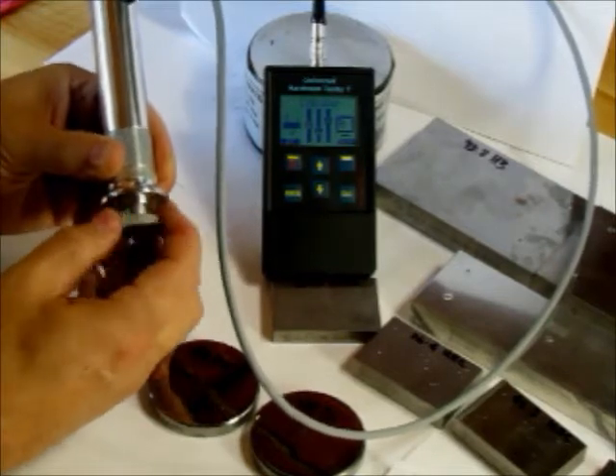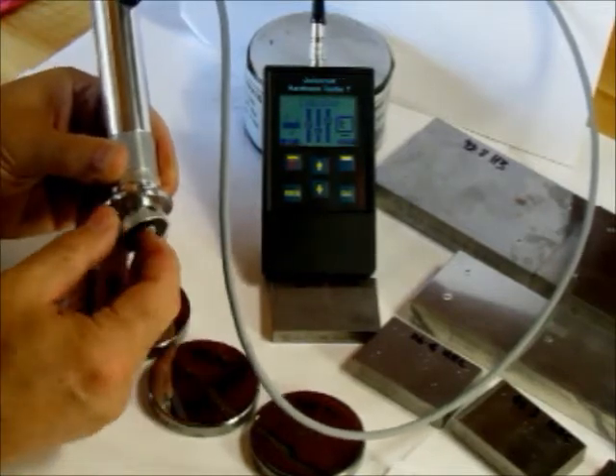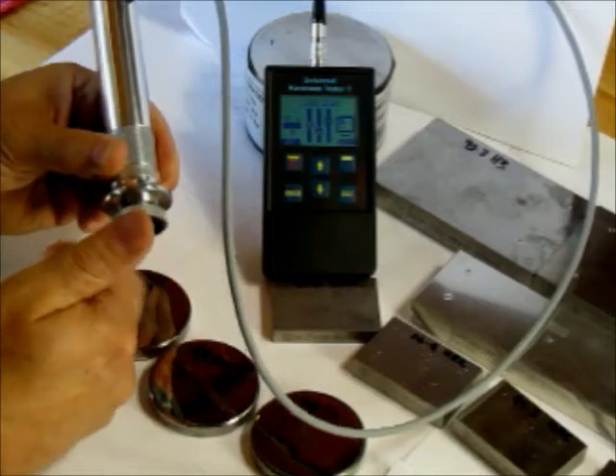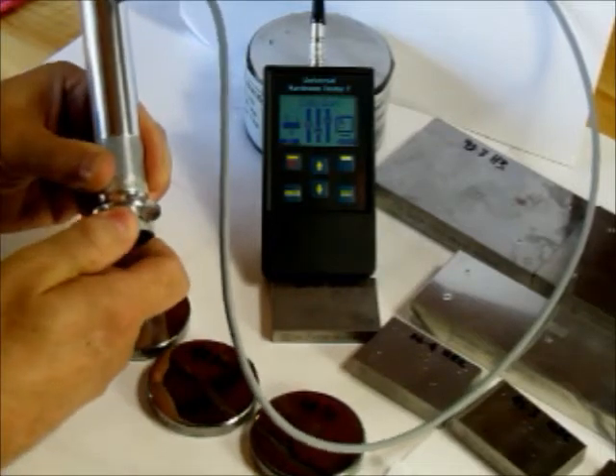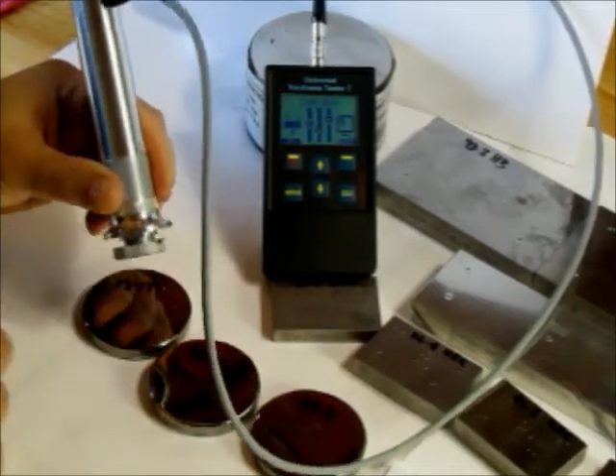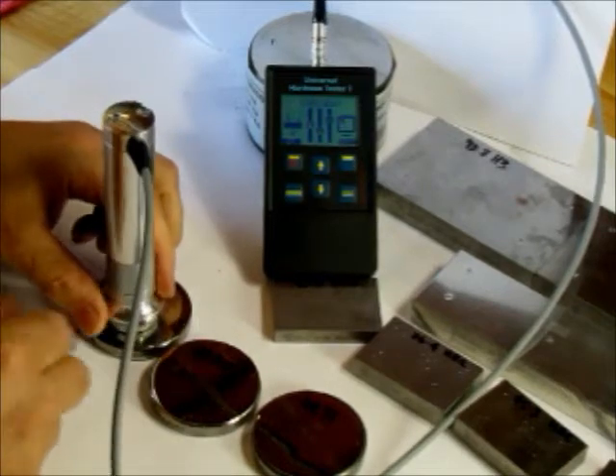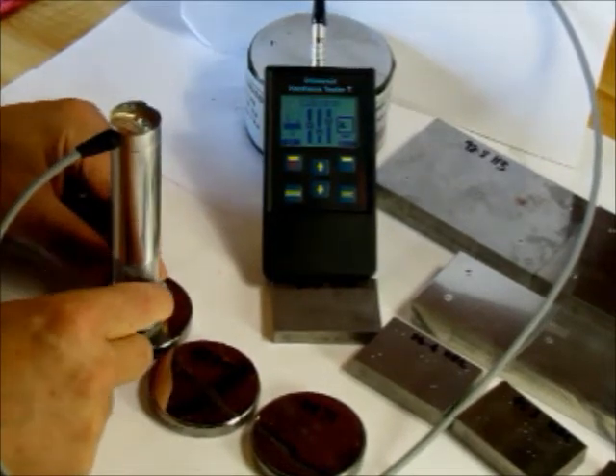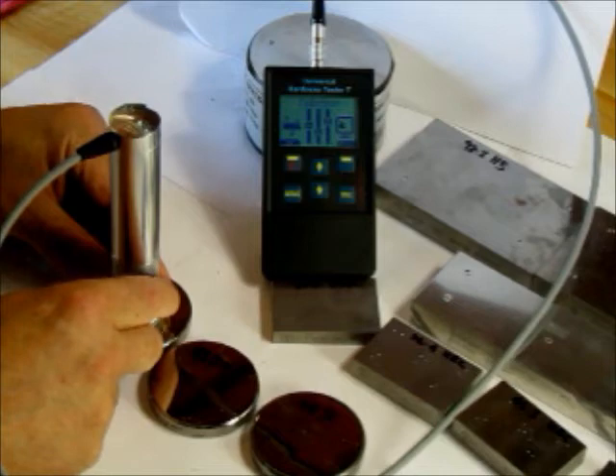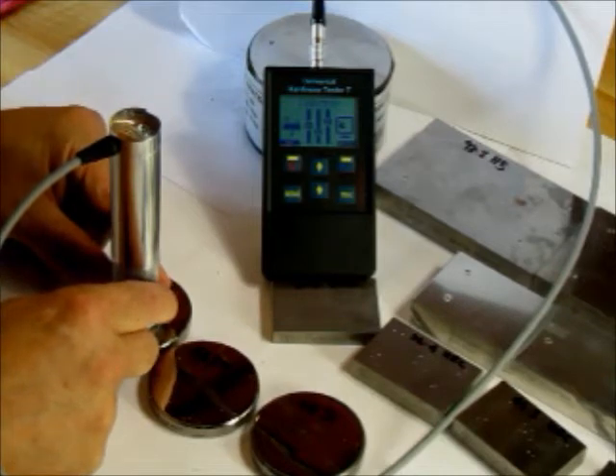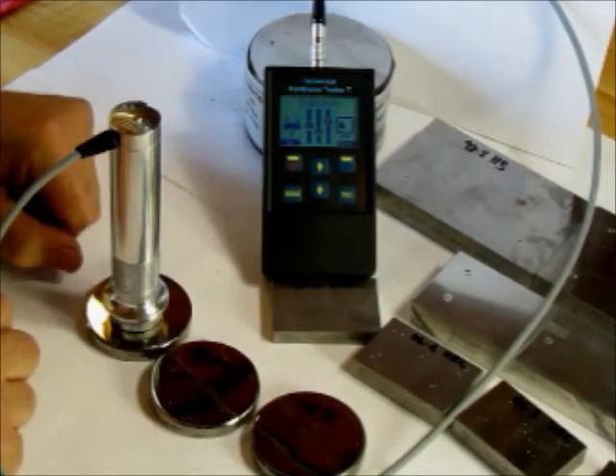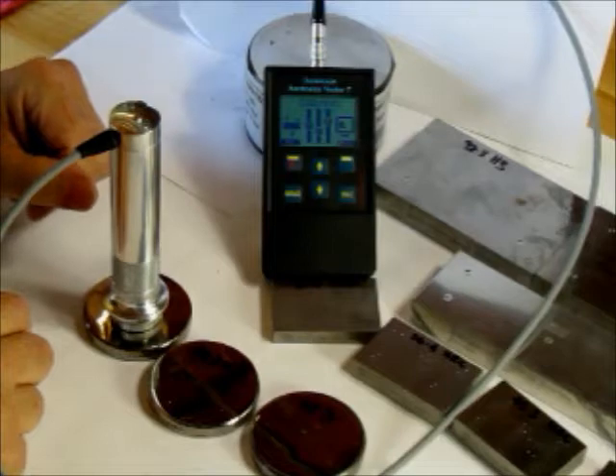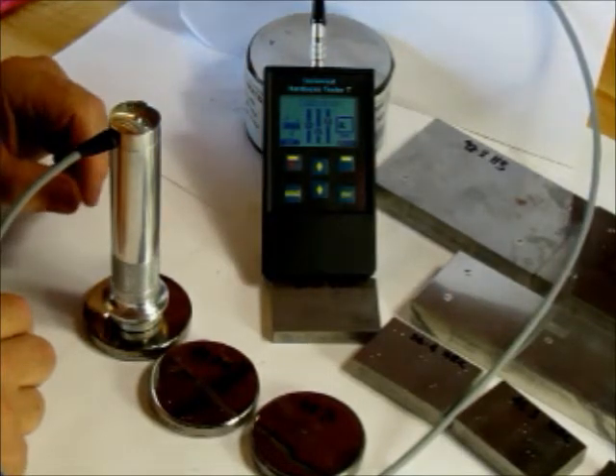This particular probe is the 10N probe, so it requires about 2 pounds of force to activate it, and we use this little puck or foot here. So to do a test, I press down. It's a two-step thing. There's the resistance and the spring first and then second, and this is as simple as the motion is.